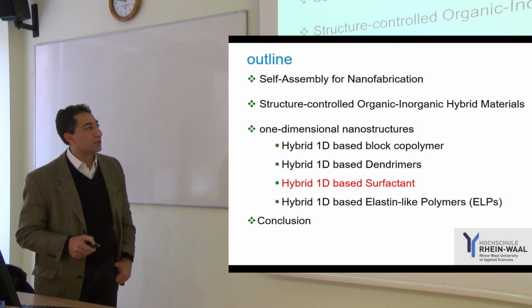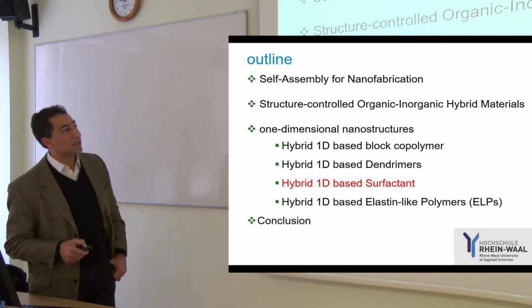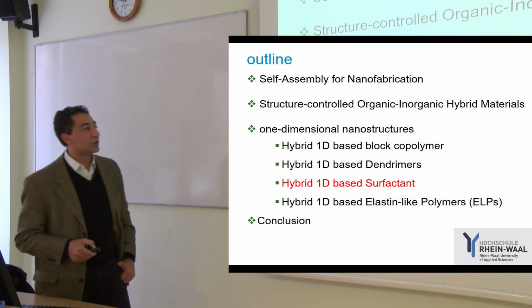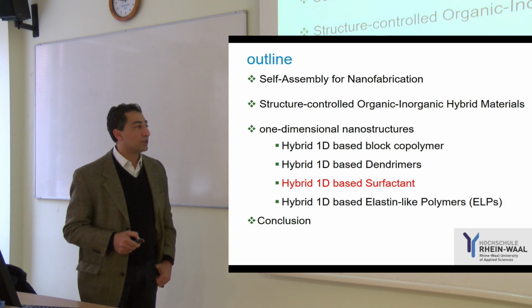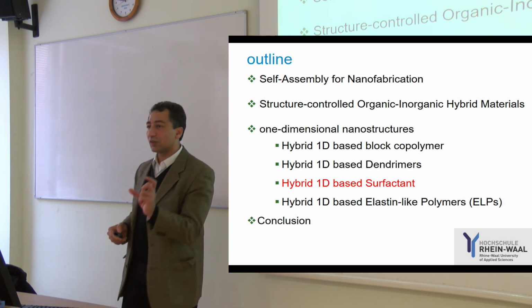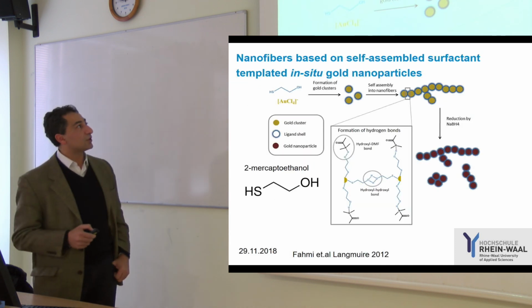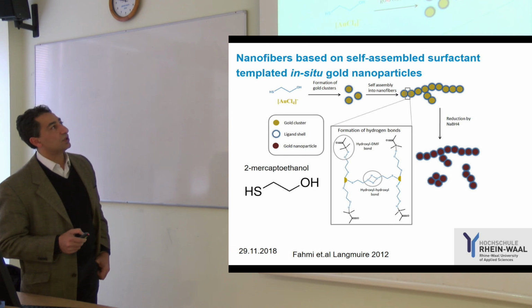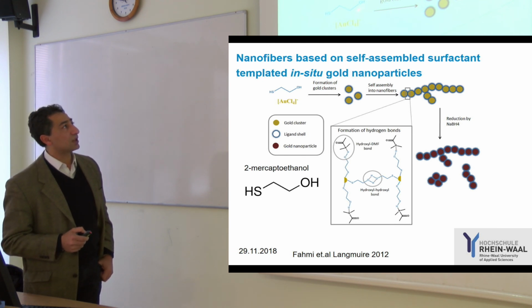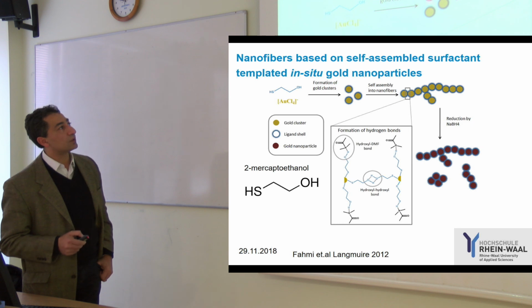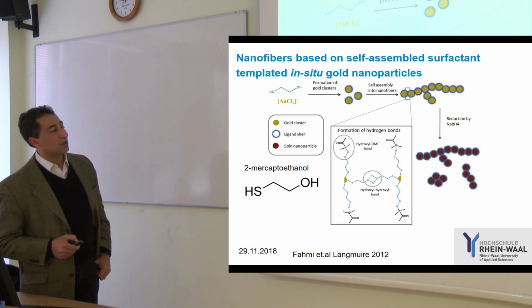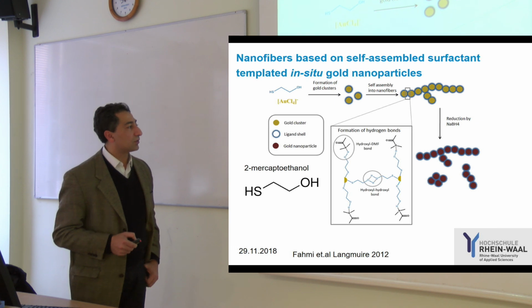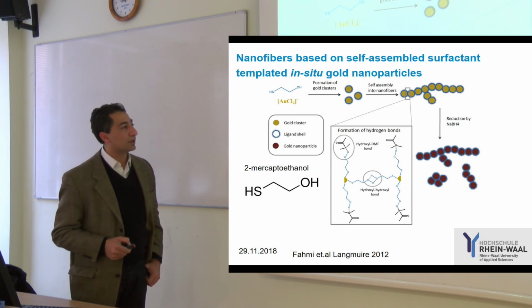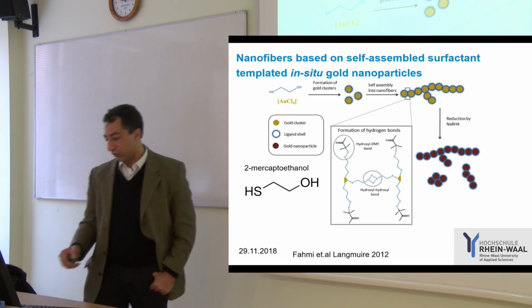After block copolymers, dendrimers, we saw this is quite a sophisticated level of architecture. Dendrimers are even more sophisticated, and need more chemistry. We try to make 1D structure using a very simple concept, using a very short surfactant. We use the same concept, what we call the in situ approach. We have a very, very small surfactant, and we use it as a starting material to make what we call a gold nanoparticle. We have two functional groups here so that we can align this gold nanoparticle in a well-defined way by using just a very simple hydrogen bond. We use 2-mercaptoethanol so that we can use the in situ approach for the gold nanoparticle, and we can have this kind of nanostructure in a well-defined way.